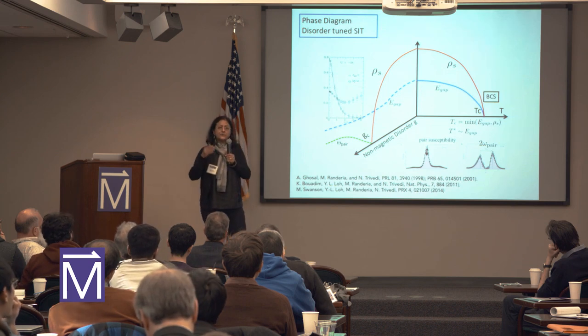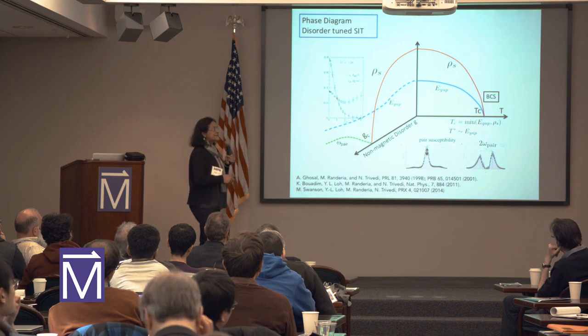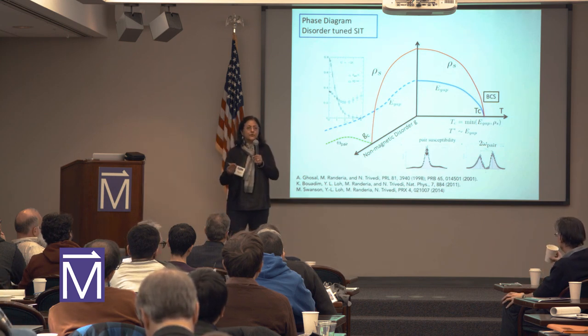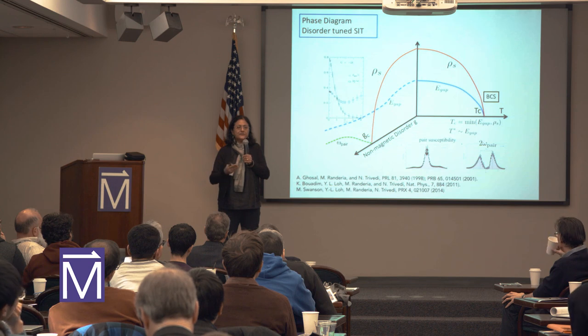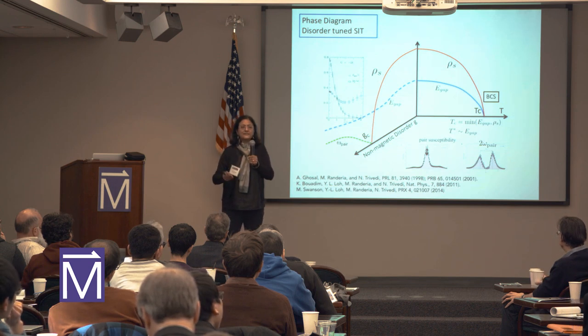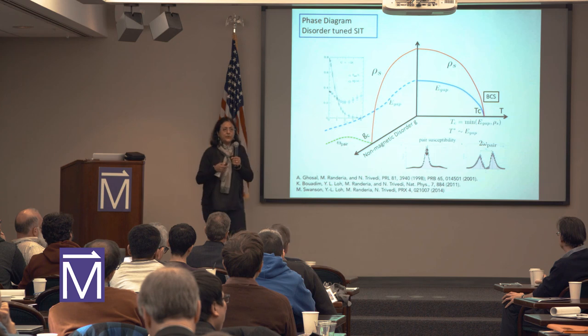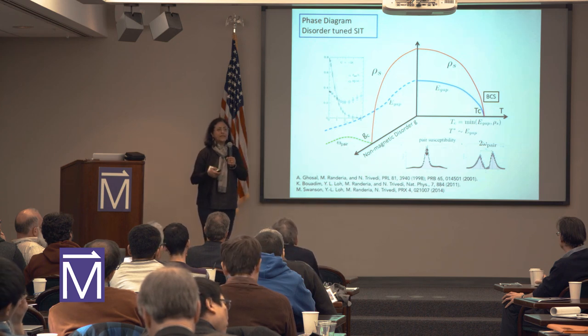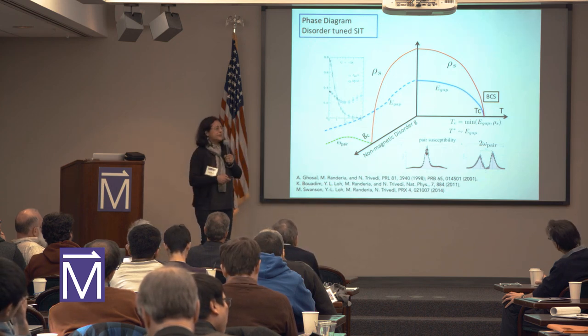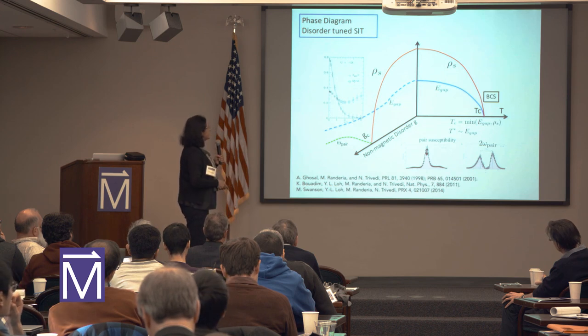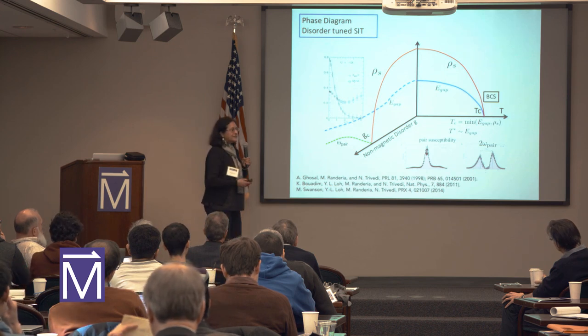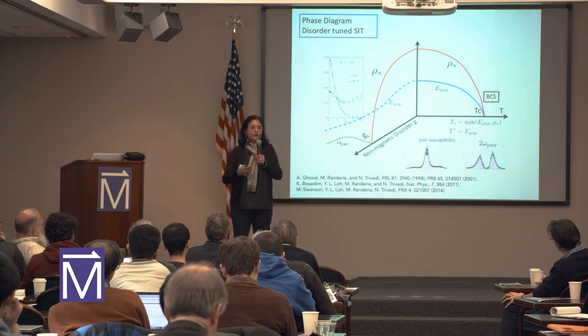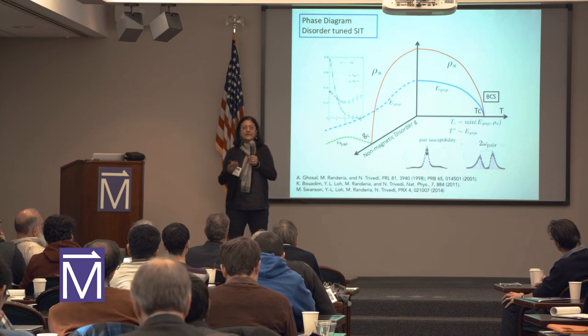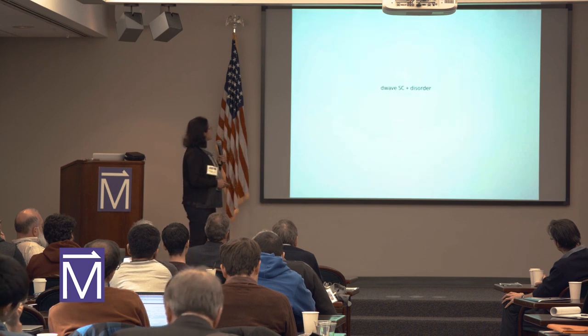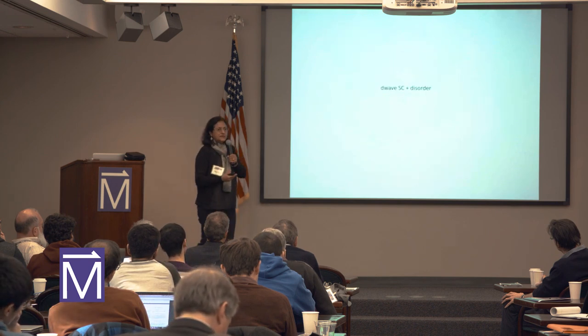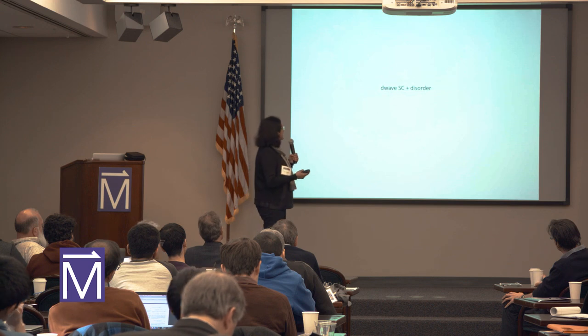Now, as you add disorder, if the superfluid stiffness is going down, there is a sum rule on the optical conductivity, and so there's an obvious question: where is that weight going? And that was the whole question of what is happening to the Higgs modes and so on. So we also address that question here. So pretty much in the S-wave case, we have a very good understanding of all the aspects of superconductivity and the insulating phases. Okay, so the next challenge was to come to D-wave superconductor plus disorder.